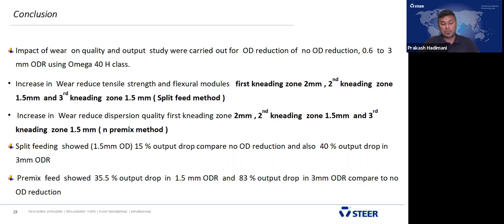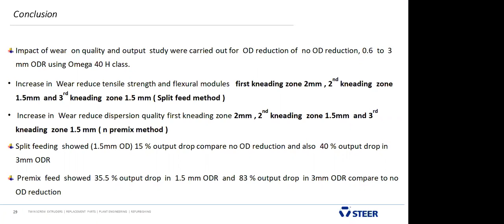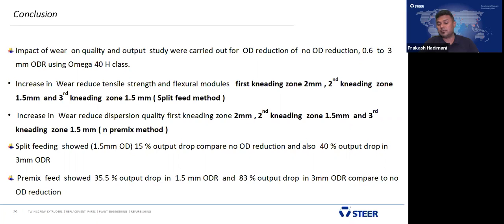And when it comes to the output, the split feed method showed a 15% output drop with 1.5 millimeter OD reduction, and a 40% output drop with 3 millimeter OD reduction. The premix feed showed a 35.5% output drop at 1.5 millimeter, meaning 0.75 millimeter per side, and an 83% output drop at 3 millimeter OD, which is 1.5 millimeter per side, compared to no OD reduction.